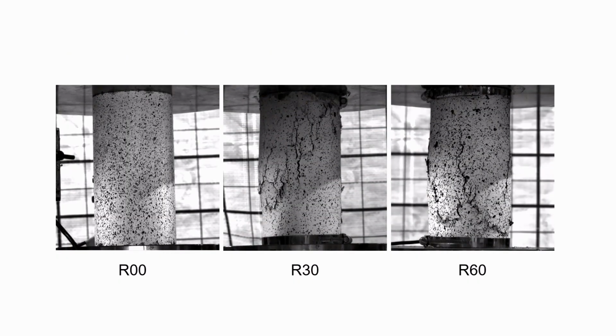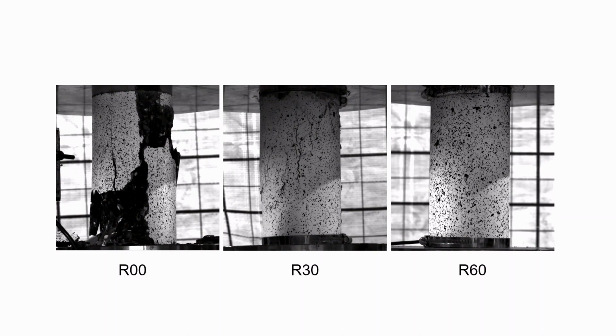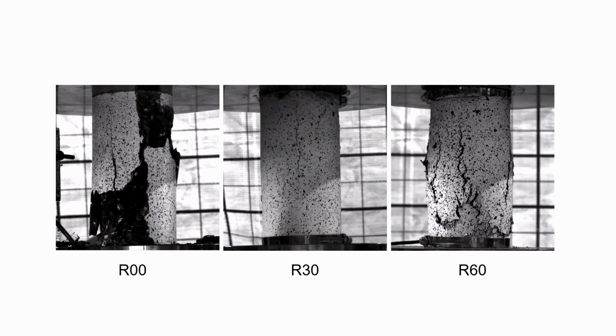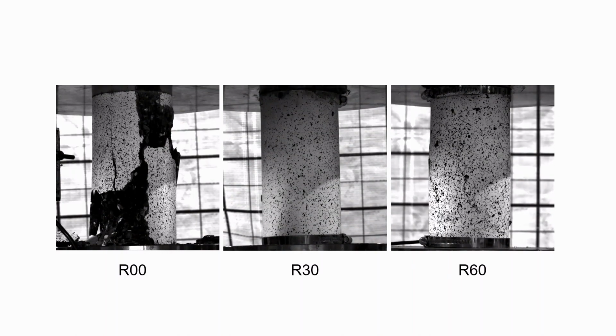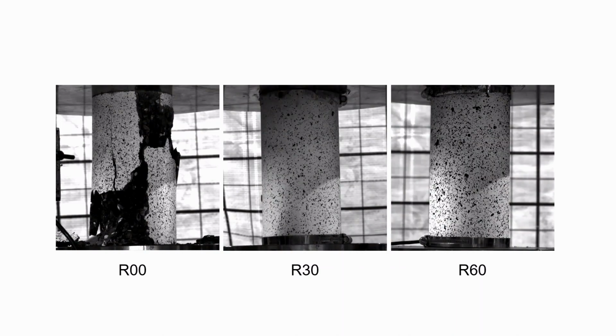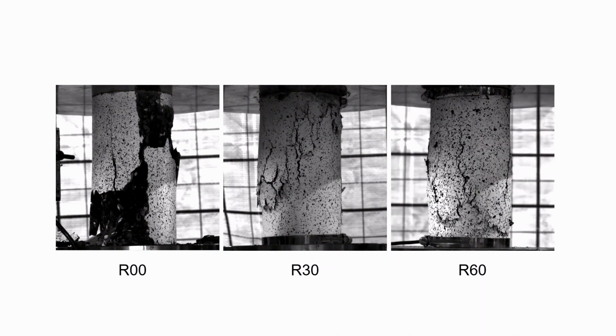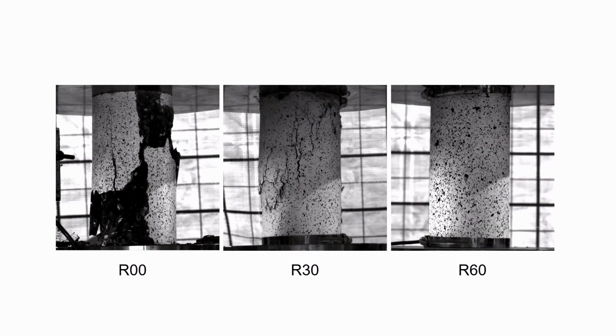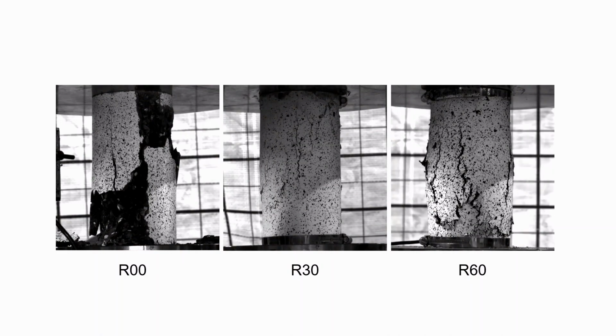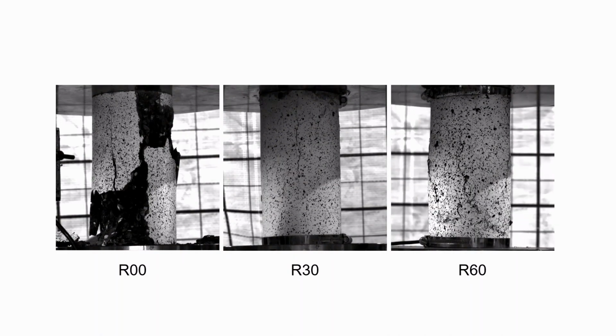But then these are the failure patterns. So the non-rubberized one, the R0 specimens, they kind of failed in a very brittle manner, whereas the ones with the rubberized concrete, I'm showing here R30 and R60, they kind of failed in a gradual manner by sliding across a diagonal crack.